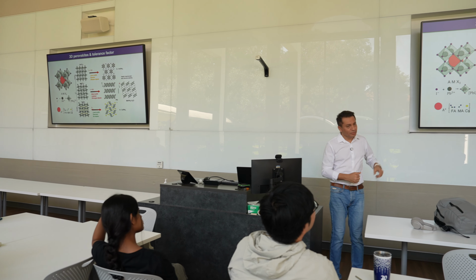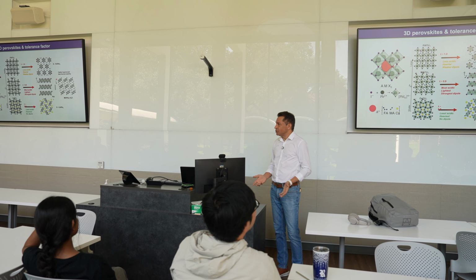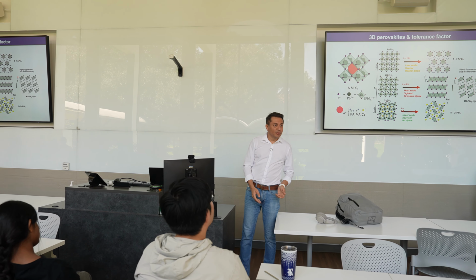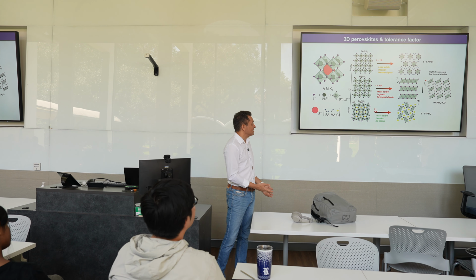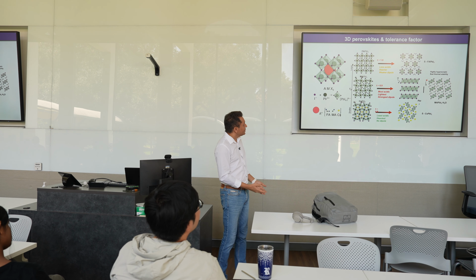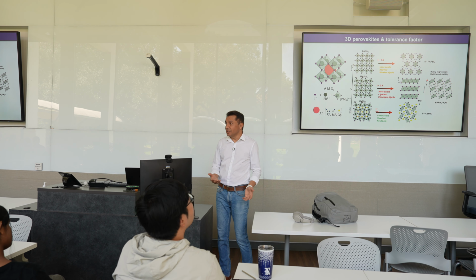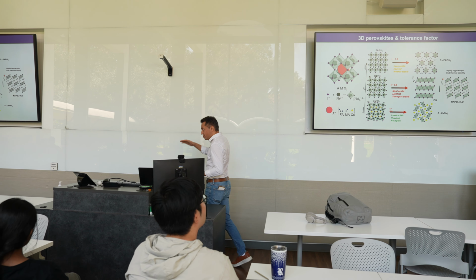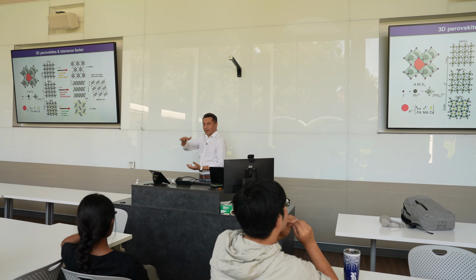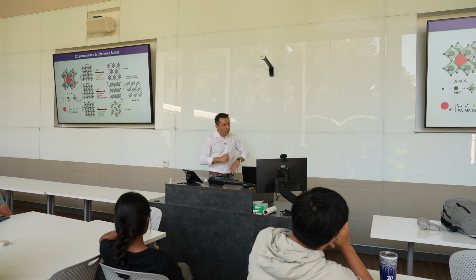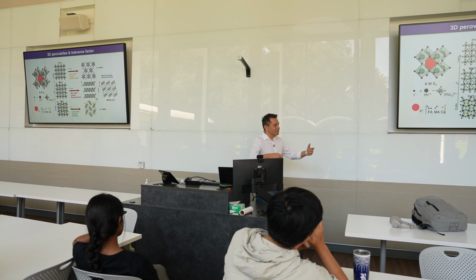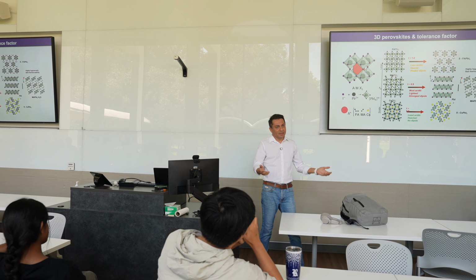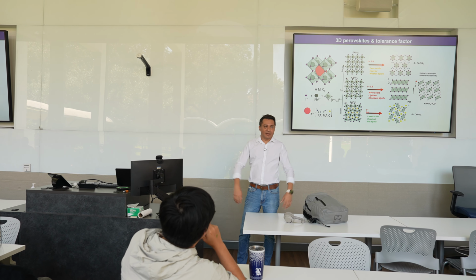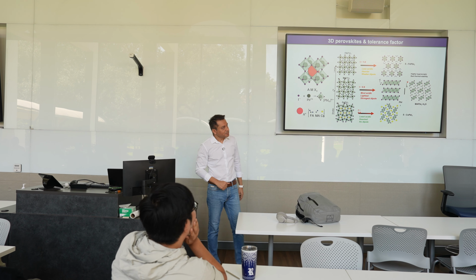And so that forms a perovskite, but it turns out that if you look at these three things, the top and the bottom don't really exist as perovskites at room temperature, right? They are in what is known as these delta phases or yellow phases, and so that's a problem, right? So either I need to do something to compress the top one, right? Make the lattice slightly smaller, or increase the bottom one, right? Increase the lattice parameters, somehow so that it actually goes up.